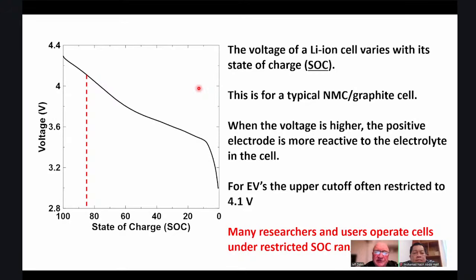And for these type of NMC lithium-ion batteries, the voltage of the battery varies with the state of charge. So when it's fully charged, 100%, it might be 4.3 volts. And then as it's discharged, it might go down to 3 volts or so at the 0% state of charge level. And what battery researchers have learned over time is that the higher the voltage, the positive electrode is more reactive to the electrolyte in the cell. And that means the lifetime gets compromised the more time you spend at the highest voltages.